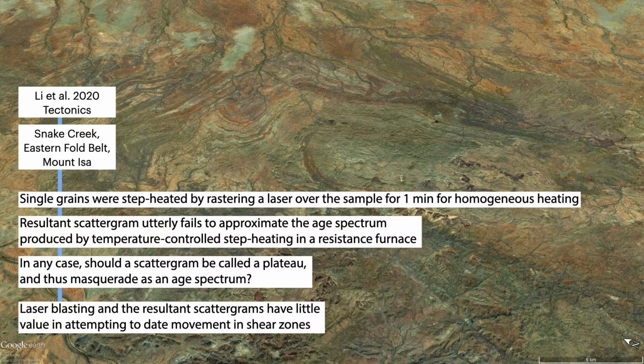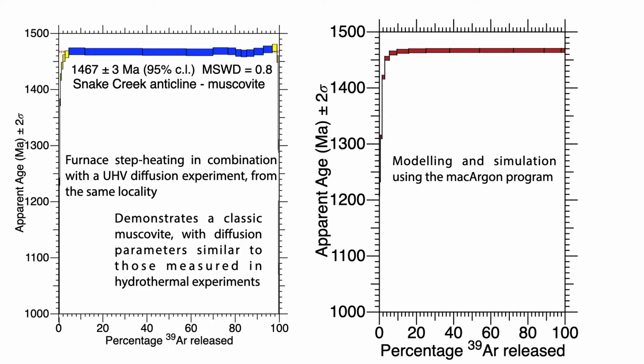So let's begin by putting to rest the idea that using a laser and all you need is a plateau. There is no theoretical or observational basis that suggests age spectra from metamorphic tectonites should approximate a plateau, except under very specific circumstances. So let's choose a particular paper to illustrate this mistake. What I can show here is an age spectrum measured in the laboratory using furnace step heating in combination with a UHV diffusion experiment. And this is from the same locality as addressed by Li et al.